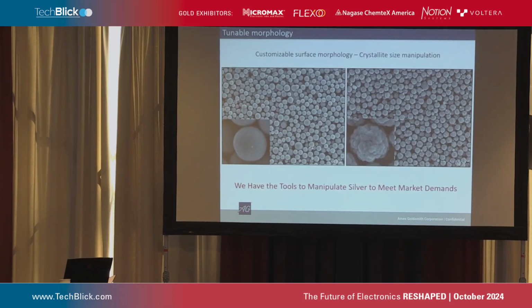This is another example of modifying the crystallite size. On the left, we have a more polycrystalline, smaller crystallite size material, and on the right, this is a larger polycrystalline material, so this is going to be on that range of 30 nanometers or so. And this can control the shrinkage in the final application of the material, either once it's fired, and so forth. These are around 1.5 microns in diameter. So same diameter and varying crystallite size due to our processing changes. Ultimately, we have the tools to manipulate most silver processes to meet these market demands.